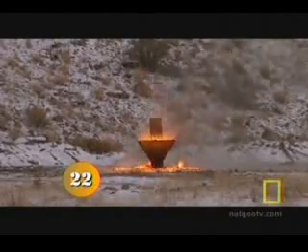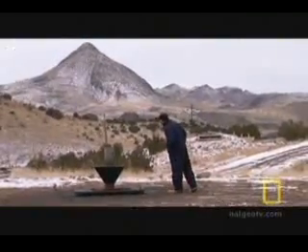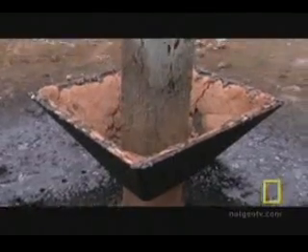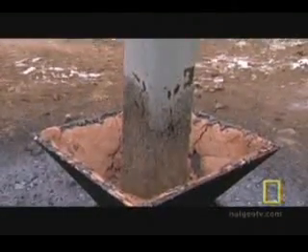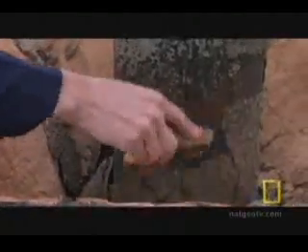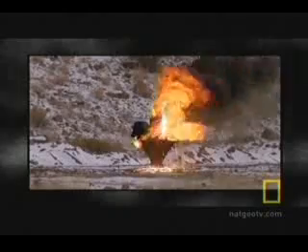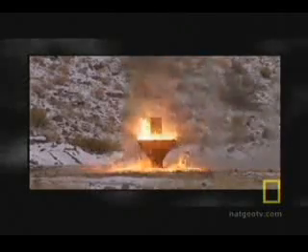The lining of clay wasn't a total success. You can see where the clay broke off. But it looks like most of the material just basically boiled out, and we did not get that heating action that we wanted on the column. Despite 175 pounds of thermite packed around the steel column, it remained undamaged. Our results seem clear. If thermite can't melt this small column, it wouldn't have had a chance to melt through the much larger columns in the Twin Towers.